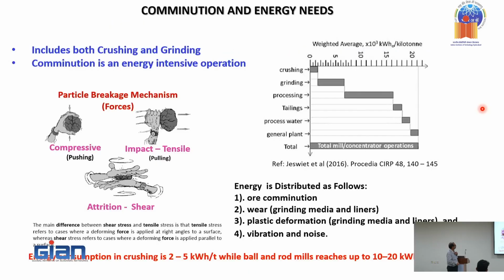Now, what do we do? The first step, as I was telling, is crushing, followed by grinding. Crushing is the primary step. This crushing is a very, very energy intensive operation. Almost 30 to 40% of the energy you are spending in the total process goes towards this particular step. And another thing is, it is the most inefficient stage. Of 100 units of energy you give here for crushing or grinding, only 1 or 2% will be effectively utilized. The rest will go as mechanical wear and tear, and so on and so forth.